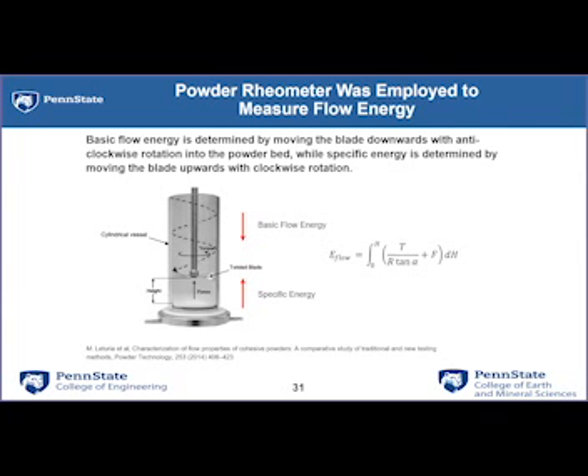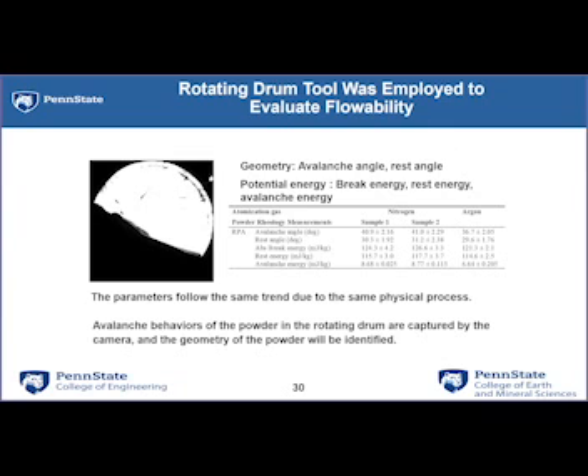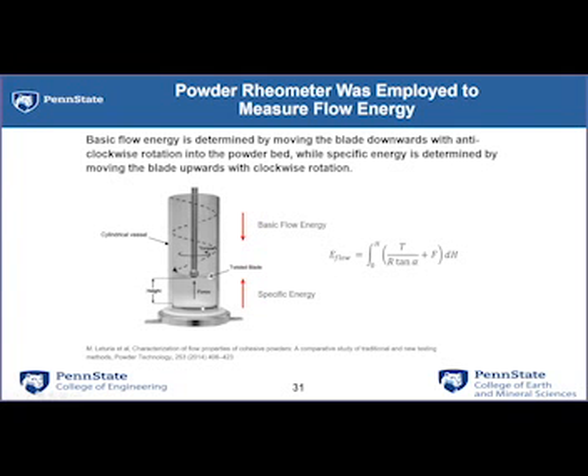I wanted to just run through how we use a little bit of these. In the rotating drum, we measure avalanche angle, and we found this tool is really good at characterizing powders in terms of how they're going to operate in a powder bed fusion system. The powder rheometers are much better at telling us about mechanical blending of powders, something you would see much more in an injection molding type system, where you might be moving a powder through with a screw driven mechanical mechanism, which is very similar to what you see in a thermal spray or a directed energy deposition type powder feeder that we have available.